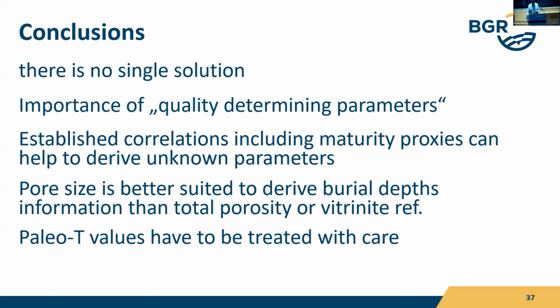If you have, for example, 3 maturity proxies, you can see if it makes sense or not. This is what I showed you with the pore size. Does it make sense? The vitrinite reflectance against pore size against burial depth, for example, then you can find and learn more about the material. So if you're not sure about burial depth, then you could measure the pore size as well. I know that it's the parameter which is hardly available. It's not measured very often. Porosity is measured quite often, but pore size not.